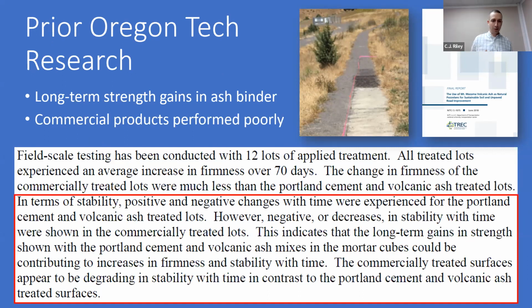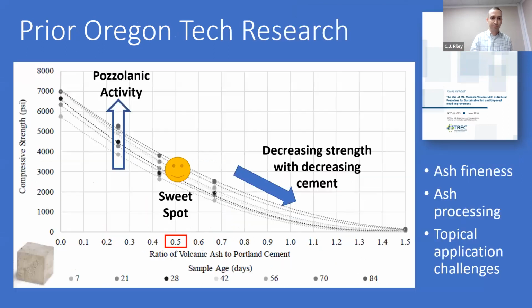So commercial products were also tested and with similar results. And the long-term strength gains for the ash cement binders appeared to improve over time, giving us an idea that this really held some promise. Some of the details of that work are shown here. This is compressive strength on the y-axis versus the ratio of ash to Portland cement on the x. As I said, thousands of mortar cubes were cast.